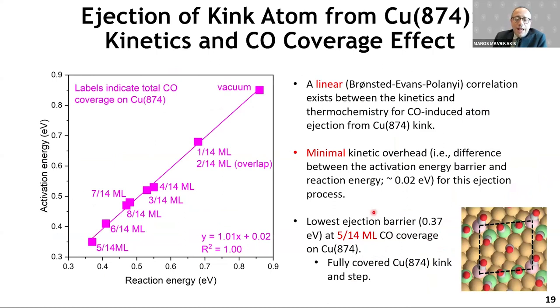So far, I've spoken about what happens in the presence of very small amounts of CO and under vacuum, the energetics needed to eject a copper atom out of the copper kink site. It's about 85 kilojoules per mole in the absence of everything, under vacuum. But then, as you can see here, the more CO you put in your environment, and if you reach the state where all the step edges and kink sites are covered by CO, which can happen at modest temperatures, even below atmospheric pressures, you see that the ejection energetics drops precipitously, to 35 kilojoules per mole. So it would be orders of magnitude more, massive ejection of copper atoms back and forth in a dynamic sense that would be relevant here.